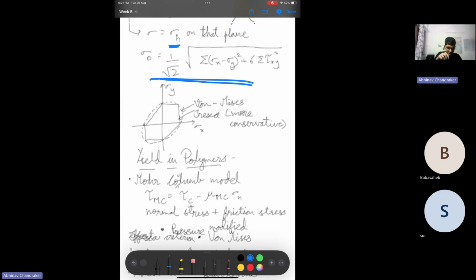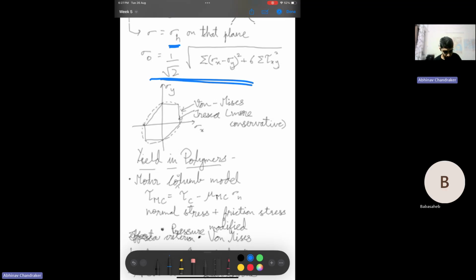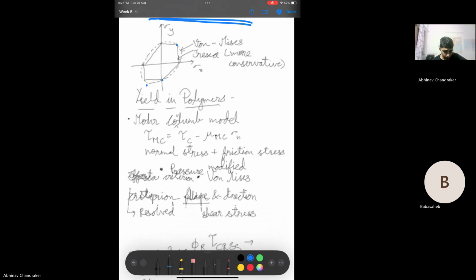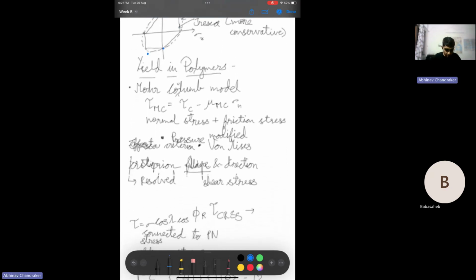Now when we look at the yield surface due to both of these, here it's shown in 2D, but in 3D also you can make this. So if you just look at sigma x and sigma y which is being applied to a material, then if the value of sigma x comma sigma y is lying outside this dotted ellipse, then it will fail according to von Mises stress. While if it is outside this hexagon, it will fail according to Tresca. So Tresca is more conservative because even in the in between region, it predicts failure. This has been very well covered by sir. You can look at that.